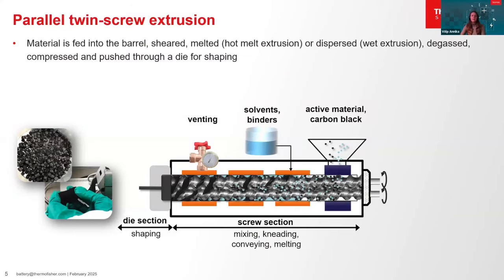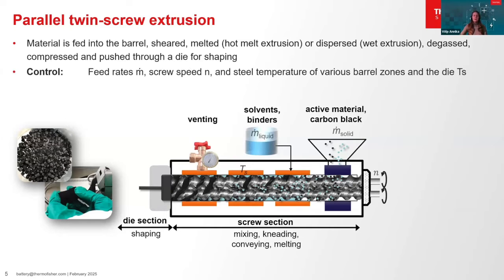In general, the task of the parallel twin screw extruder is to apply thermal and mechanical energy to create a dispersion and shape it. Solid materials such as the anode or cathode active material and carbon black are fed into the extruder barrel and sheared. During melt extrusion, a polymeric binder is added, which is melted in the heated twin screw barrel. In wet extrusion, solvents and binders are added to the barrel via a liquid feeding system. All materials are mixed, sheared and compacted and pushed through a die.